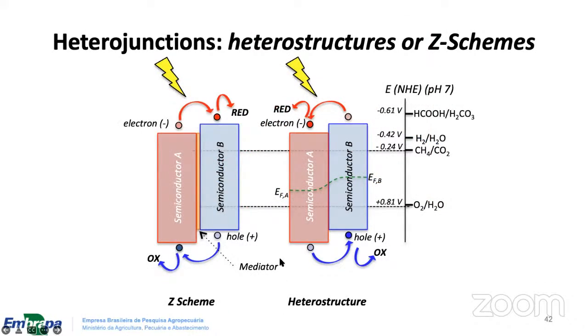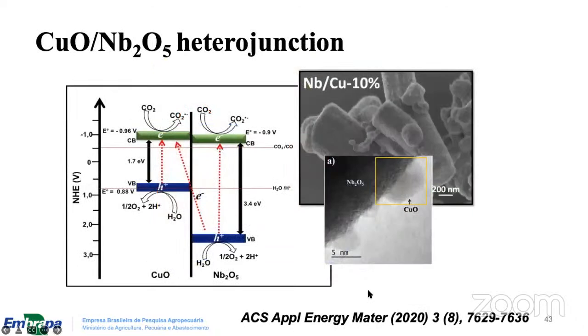The idea is to join the system with another semiconductor that can promote the separation of the electrons, by pumping out the electrons to one semiconductor and keeping the holes in another semiconductor. Our choice for that system, that could be a Z-scheme or a heterostructure, doesn't matter at that moment. But the most interesting is to understand this in a practical example. For instance, the copper oxide supported over niobium oxide. Why niobium oxide? The idea was to find an oxide that could be much more stable than the copper oxide. In other words, a system that at the end of the reaction could oxidize the copper oxide again, if the reaction goes with this model we have proposed.